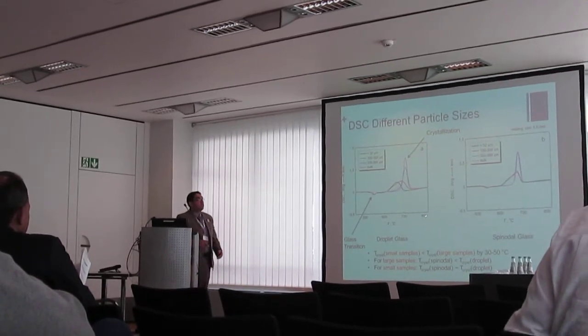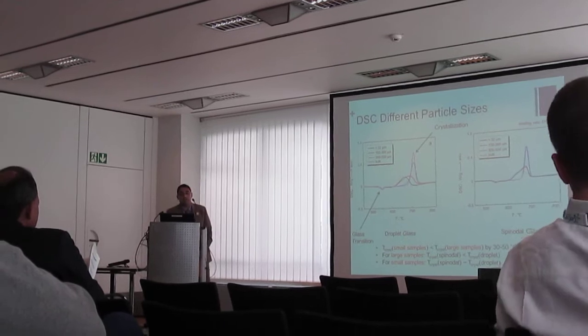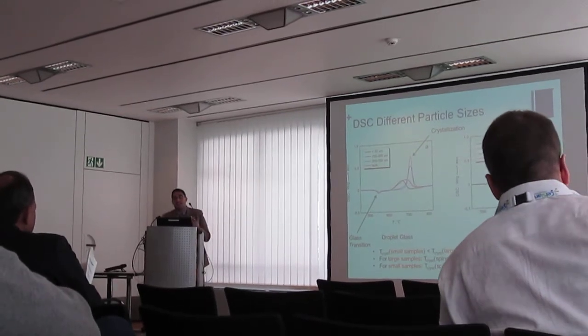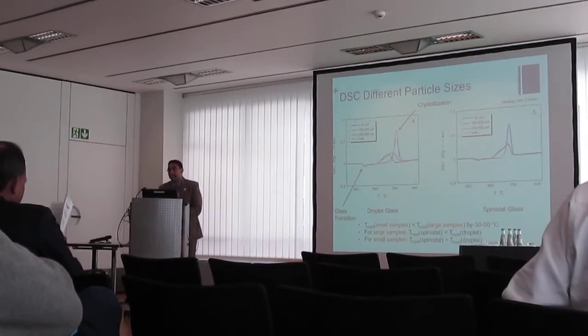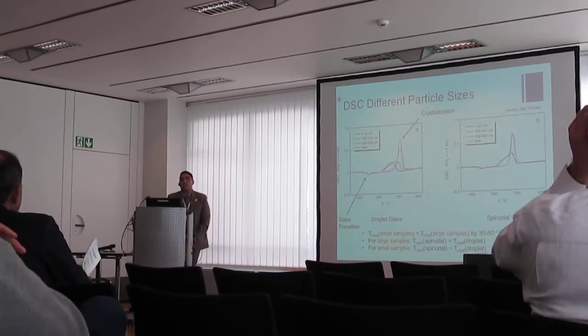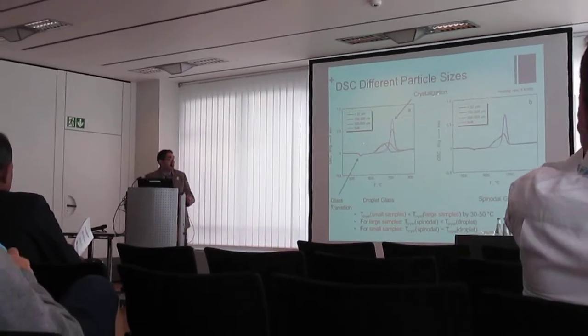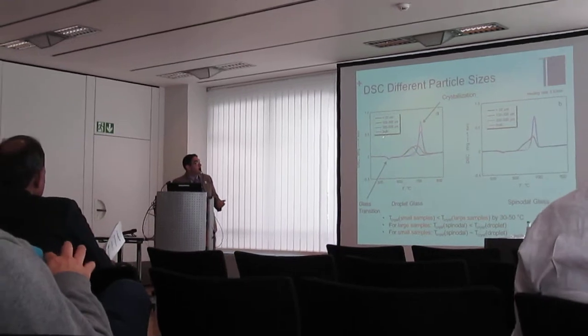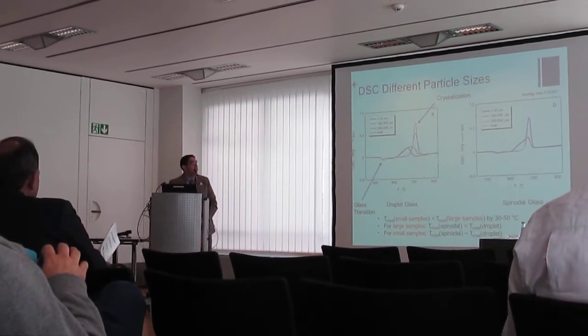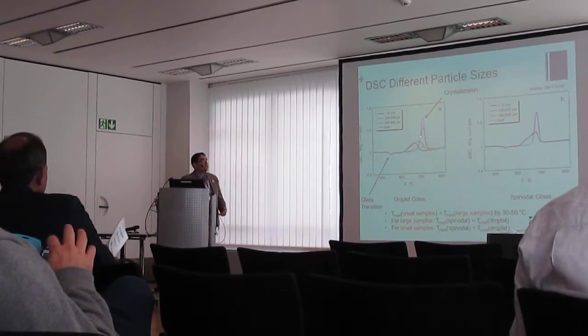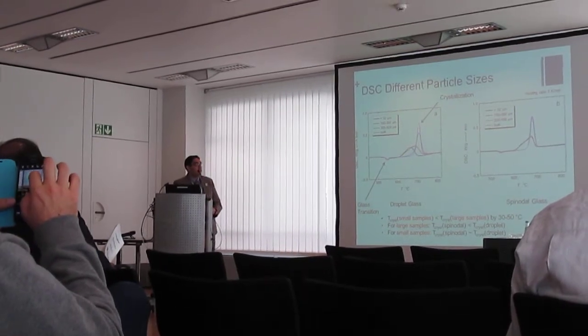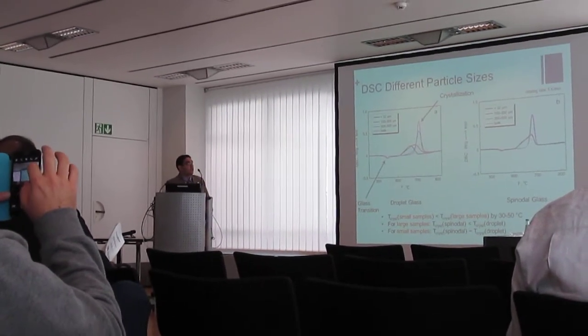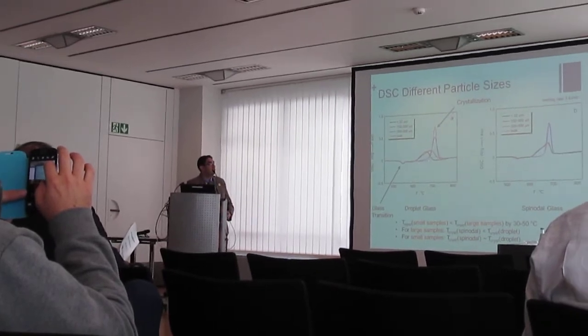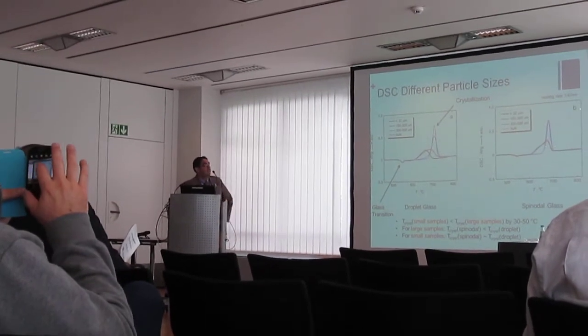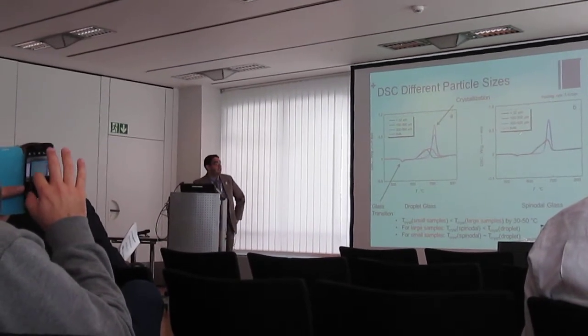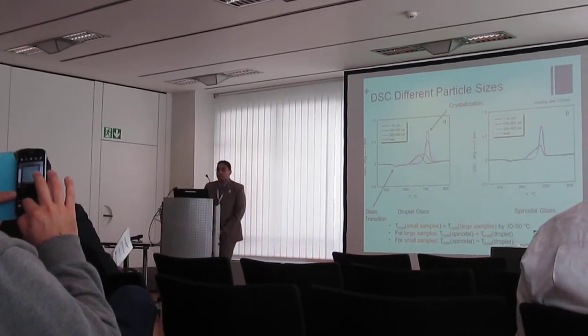From these two graphical data sets, we can see three points. First, the temperature of crystallization for the smaller samples, less than 32 and 150 micron, is lower than the crystallization temperature for the larger samples by about 30 to 50 degrees Celsius. This is true for both the droplet and the spinodal glass.